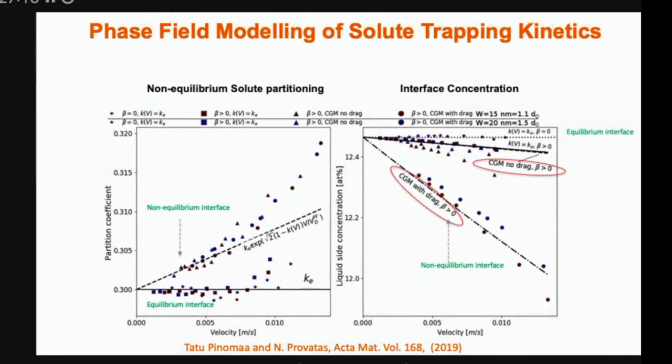And so long and short is we took a phase field model and we matched it. We added some contributions to mass transport to allow trapping at the interface to occur, thus emulating the non-equilibrium partitioning of solute, which we think is important to take you out of this dendritic regime that occurs really when you're locally equilibrated. And here's an example of the models before and after. On the left-hand side here is the equilibrium partition coefficient. This is the ratio of solid to liquid concentration at the interface as the model is running in full dynamic mode.